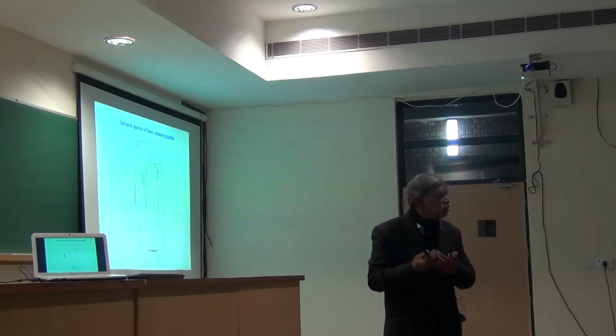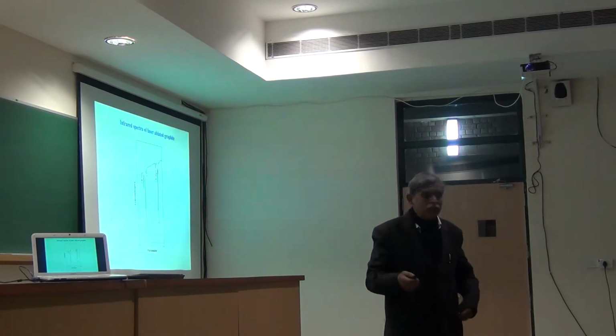So this is the spectrum that we got. Of course, this is nothing new. The whole world had recorded it by then. But the moment you set up a new facility, as we did, we like to know whether it works. So you take graphite and you record the spectrum and make sure that you get the same spectrum which the entire world had covered by then. You do it, and here you see a C3, you see a C5, you see a C7, all of these structures. The spectra were known, and we were getting them. They sort of told us that we were doing things right.